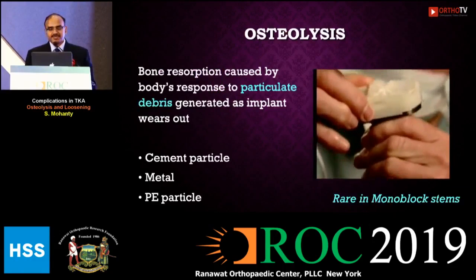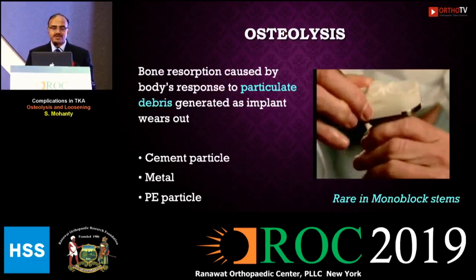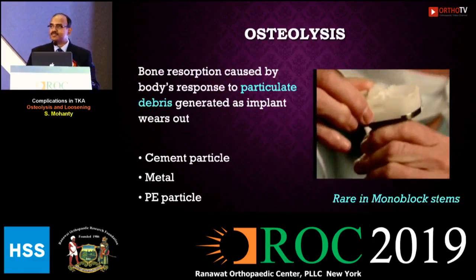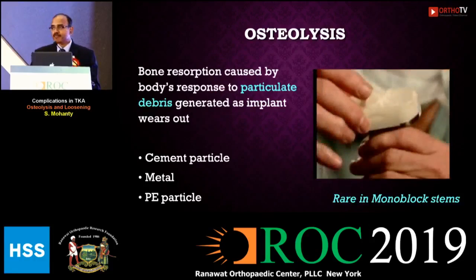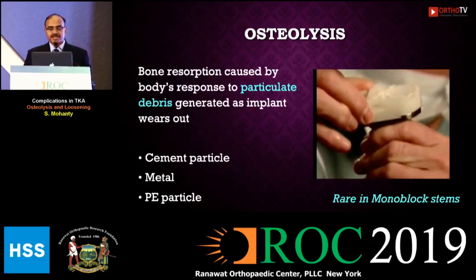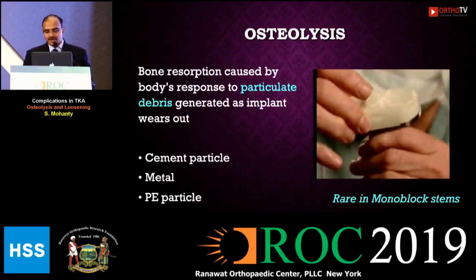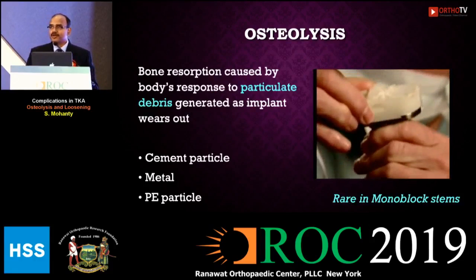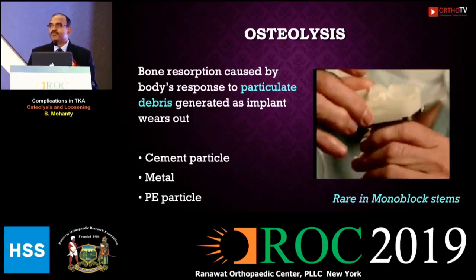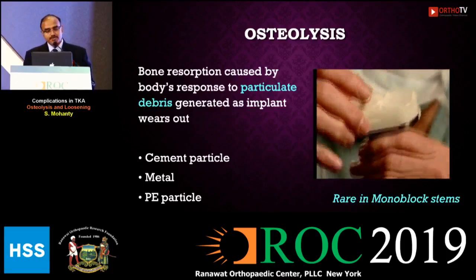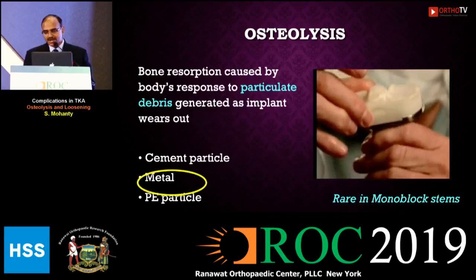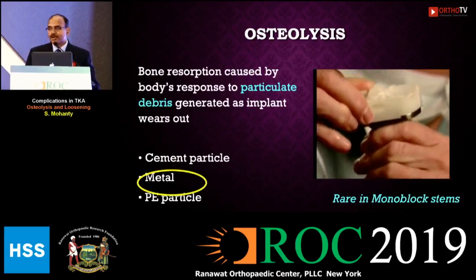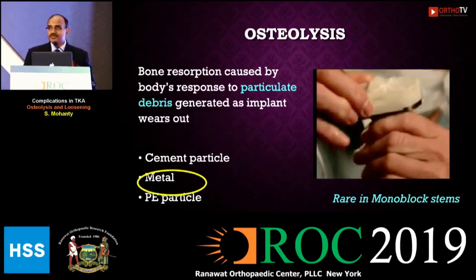Osteolysis has been defined as bone destruction caused by the body's response to particulate debris generated as the implant wears out. These debris can be cement particles, metal particles, or polyethylene particles, each causing different reactions, but most is due to polyethylene particles.